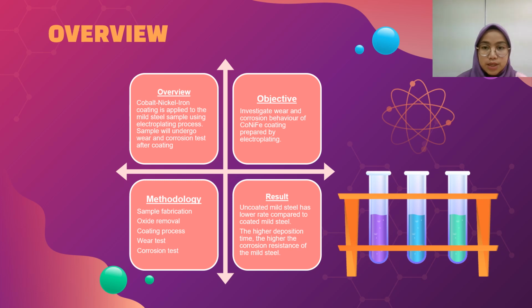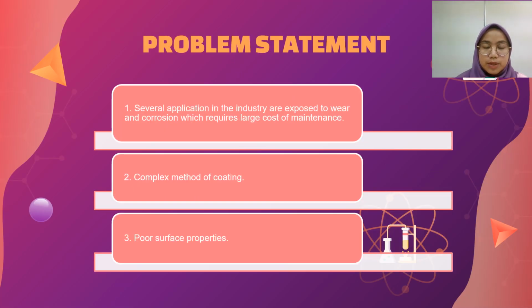For methodology, the main process are sample fabrication, oxide removal, coating process, wear test, and finally the corrosion test. The preliminary result from this study shows that the coated mild steel has lower wear rate compared to the uncoated mild steel. While for corrosion behavior, it can be deduced that the higher deposition time, the higher corrosion resistance of CoNiFe coated sample.